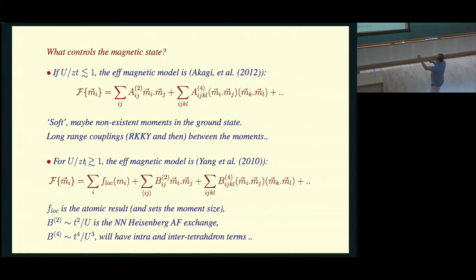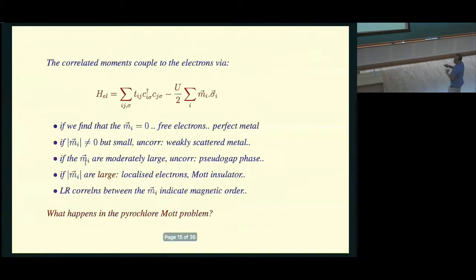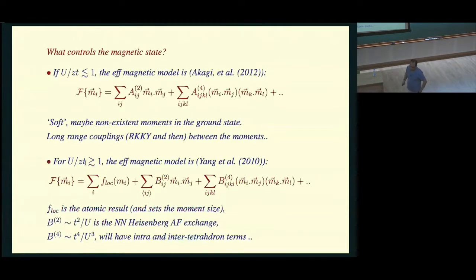The magnetic moments would have to be induced. They're not there to start with. While if you're in the strong coupling limit where the moments exist to start with, in the atomic limit, you will get a local part which has to do with the size of the moments. This is the Heisenberg term, and there are additional four-spin interactions, etc., that come up to higher order. So basically, these are approximate forms of effective magnetic Hamiltonians on the metallic side, or the small m side, and the large m side, and the fermions are coupling to these moments to generate their density of states, transport, etc. Absolutely. So if you take the nearest neighbor version, you will get the nearest neighbor Heisenberg model.